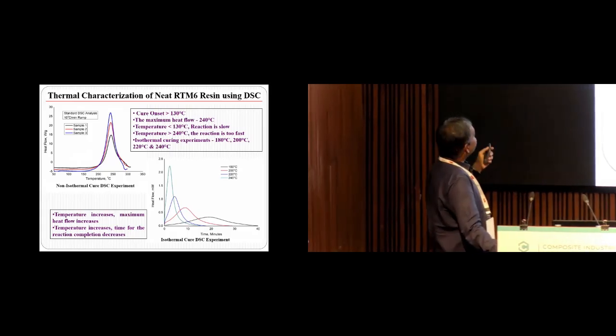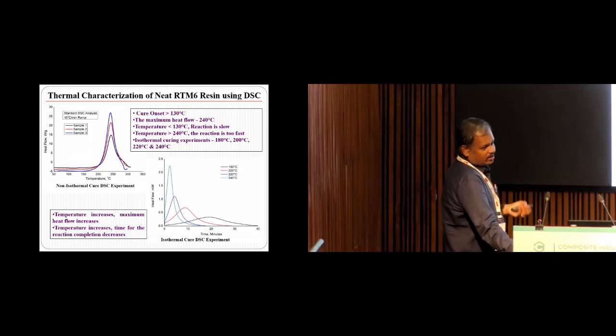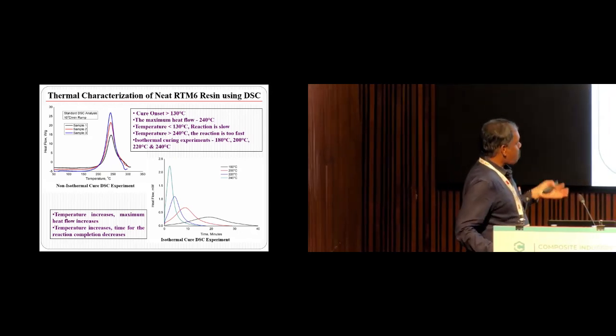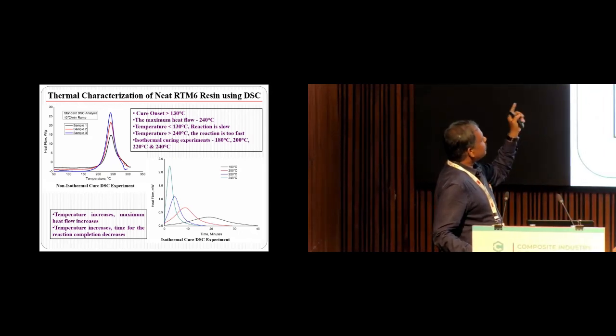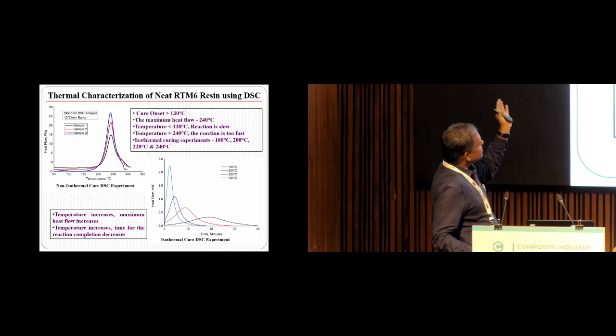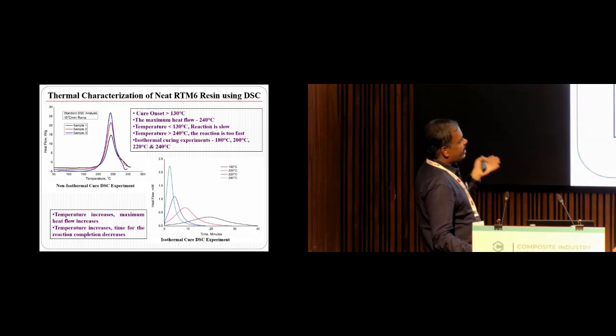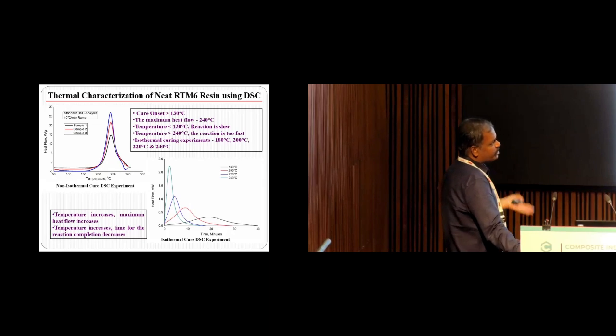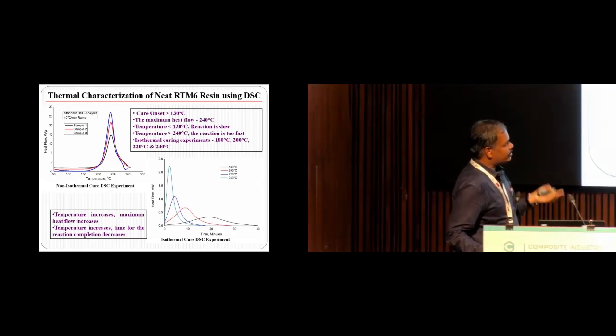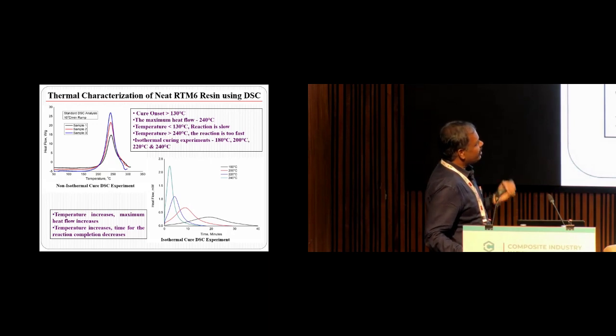As I told, I have performed the curing studies in DSC at a ramp of 10 degrees per minute. You can see 3 plots here. You can find out the onset temperature and the peak temperature, and you can see that the onset temperature is almost 160-170 degrees centigrade, and the peak temperature is almost 240 degrees centigrade. So isothermal curing can be conducted at 4 different temperatures: 180 degrees, 200 degrees, 220 degrees, and 240 degrees. That is what was performed in the isothermal DSC experiments.